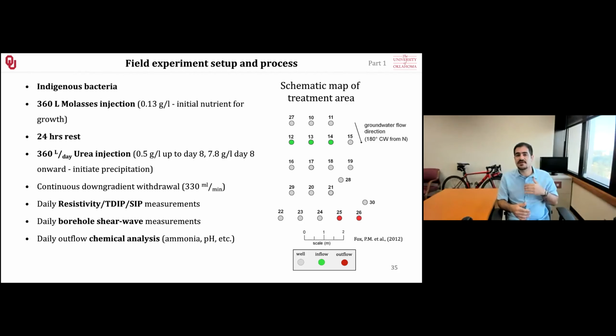Initially, we injected with a small concentration. That was not as effective. And then after 8 days, we decided to increase the concentration of urea. So we increased the calcite precipitation much more, because we didn't have enough time to stay in that field. We only had 20 days.